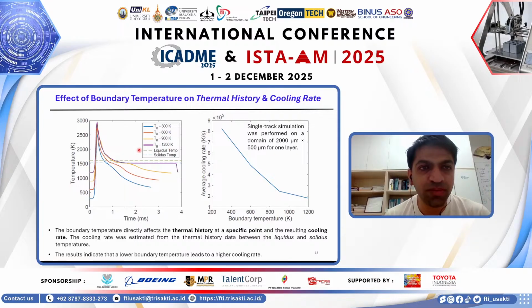Here's one of the results of the simulation that talks about how the boundary temperature of the 3D printed part has an impact on the thermal history, which is the temperature versus time graph that you see, and also the cooling rates. So you can see that when the boundary temperature is very high, the cooling rates tend to be very low, which means that it takes a long time to cool. So therefore, the grain sizes are much bigger. The average grain size is bigger.